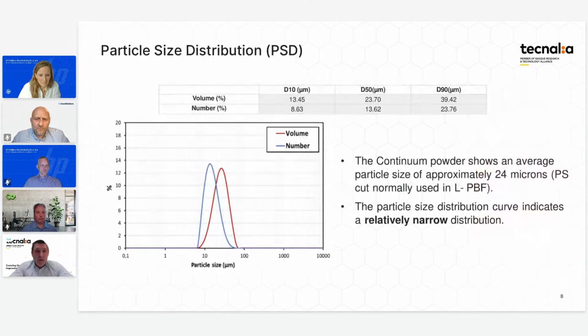So going to the particle size distribution, the powder that we got from Continuum shows quite a monomodal particle size distribution, quite similar to the laser powder bed fusion powders. We compare that to the typical binder jetting process. In this particular case, we can say that we have a slightly coarser particle size compared to the typical particle size used in the binder jetting process. However, due to the liquid phase sintering of this material, as you will see later on, the densities we obtain with this powder are good, although the starting powder particle size perhaps is slightly coarser than the typical.